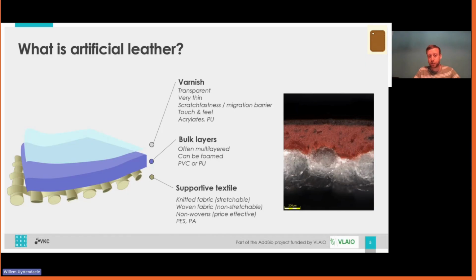Quite often, these artificial leathers are made out of PVC, so PVC plastisols, and then the varnish on top is commonly an acrylate or a PU. What we have done at Centexbel is we developed an alternative for PVC plastisols, which uses PHA, so the biopolymer PHA. We mix it with a plasticizer, and this gives a liquid paste. This paste can then be applied on top of a textile, heated and cured into a homogeneous coating in a way very similar to how PVC plastisols are applied.